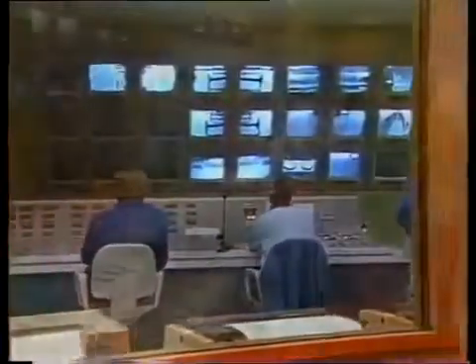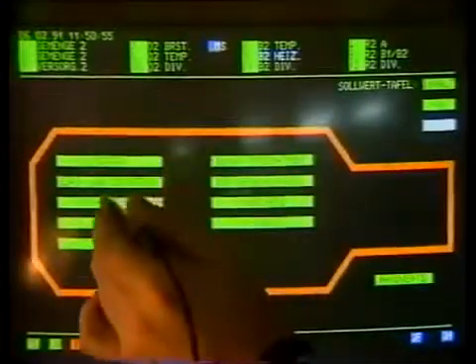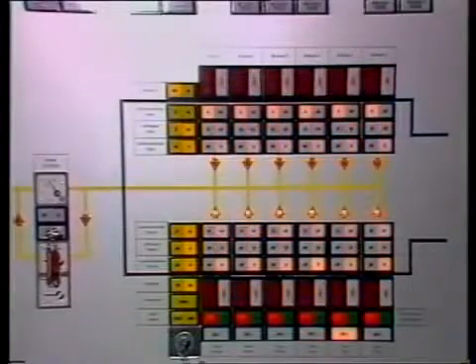Processes within the furnaces are managed from the control room to ensure that the glass is homogenous and free of bubbles. Inside the furnace, heat is applied from alternate sides in 20-minute cycles. This assists fuel efficiency by ensuring that combustion takes place in the presence of pre-heated air.